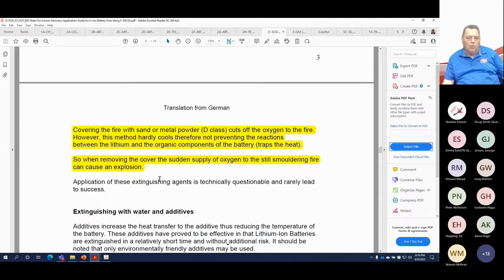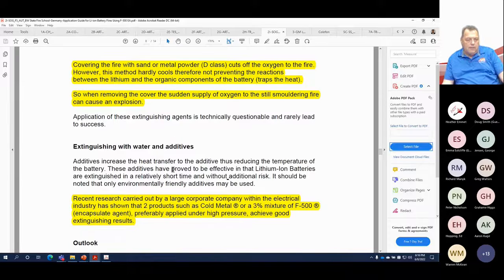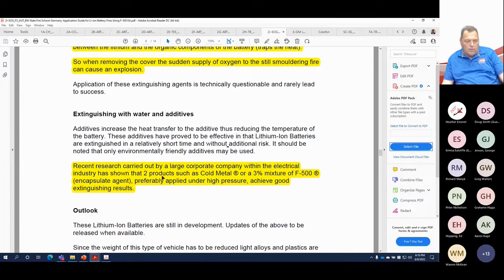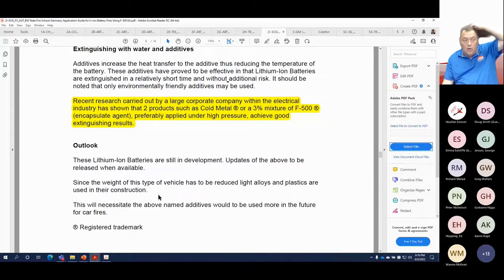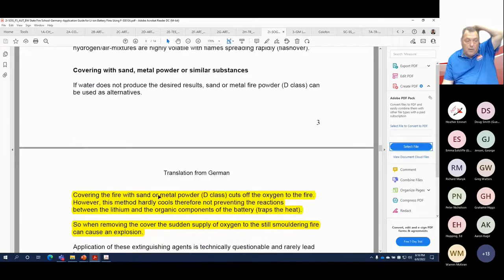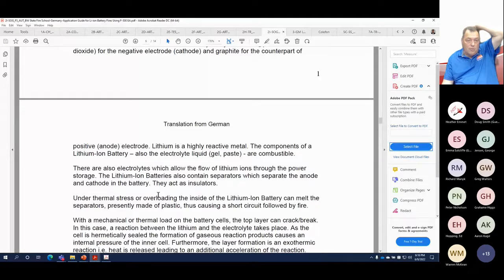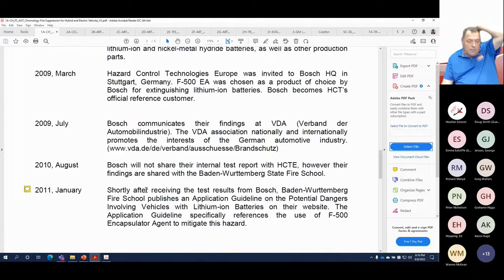So they were looking at water, they were looking at using sand and covering. And then here, they said research carried out by a large corporation within the electrical industry, they're talking about Bosch, had shown that there were two products, such as cold metal, which is a gel, and 3% F500 mixture, which is an encapsulating agent applied under high pressure, achieved very good extinguishment results. So Bosch was the one that kind of got us started here in the lithium-ion battery application. So this is one of the early on reports. As you see, we're moving forward.